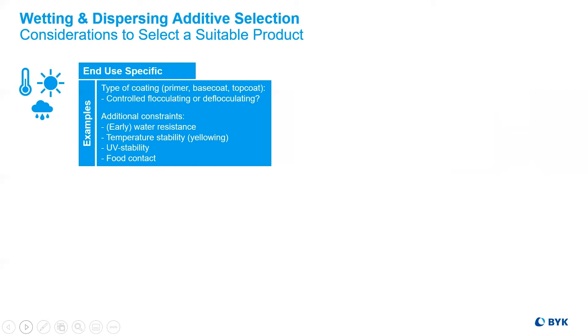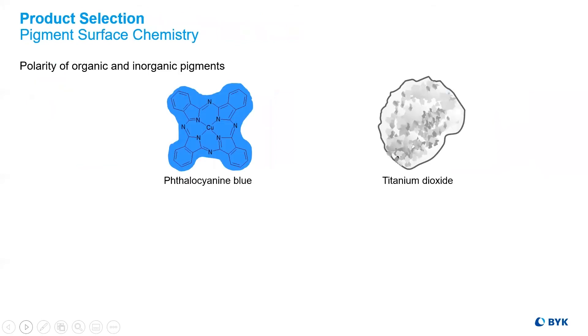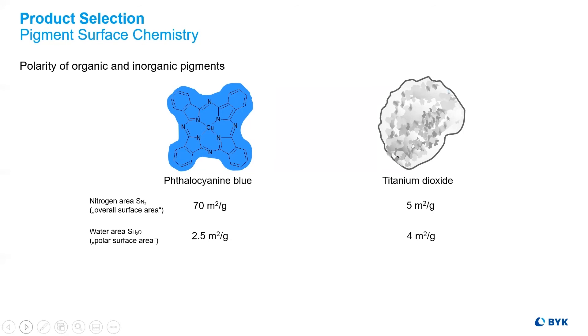All of those things really started to meld in a way that enhanced our ideas of what wetting and dispersing additives could be. The discussion of how much to use became critical with more particularly expensive pigments that were becoming on the market, particularly when compared to titanium dioxide types. The surface areas of inorganic pigments are small and the need for wetting is relatively low. Organic pigments came with the problem of nonpolar surfaces, and these areas were traditionally using other additives.